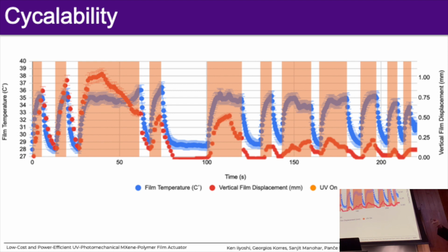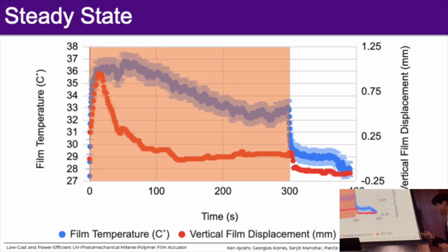The temperature of the film stays, but as we go through the cycles, you can gradually see the vertical actuation of the film going down. And to be honest, for this particular optimized film, we couldn't do any more cyclability testing because we accidentally tore it and we were running out of time. But aside from that, we were able to do the steady state test, which also showed a similar slump with longer irradiation. While the UV was on, the temperature was also decreasing, but much more so was the actuation of the film. And once we turn off the light, they both immediately go down.